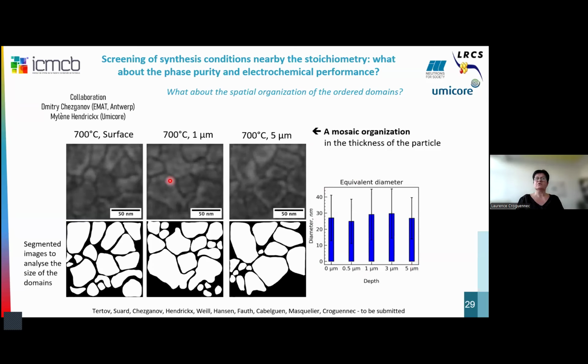All these gray-white areas are associated with ordered domains. And what is much more interesting is that, contrary to what we could have expected, a core-shell effect due to this oxygen loss during the synthesis, we have in fact a mosaic effect, with ordered domains here and disordered ones here at the boundaries.